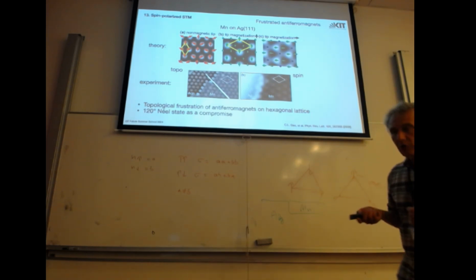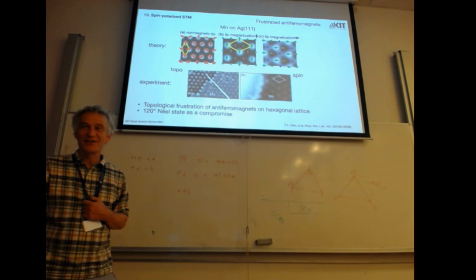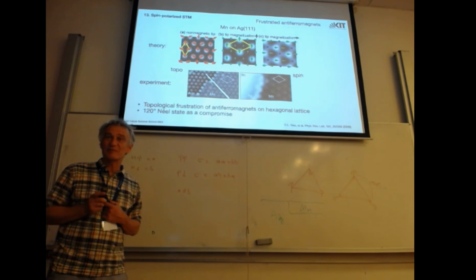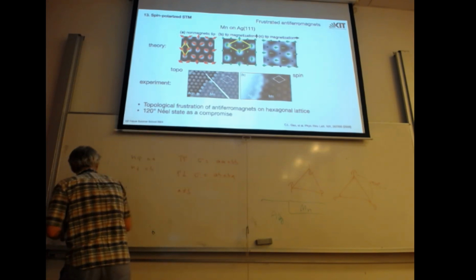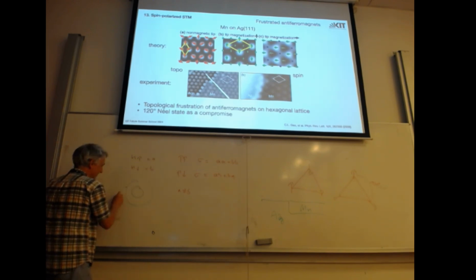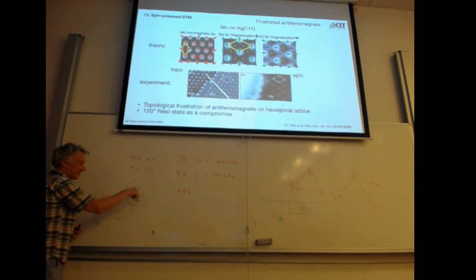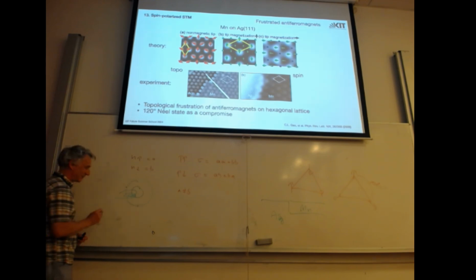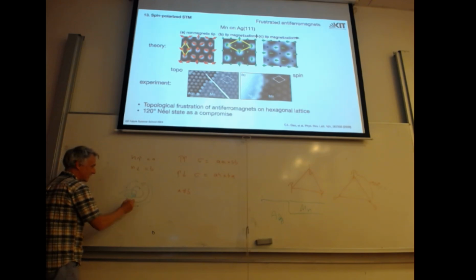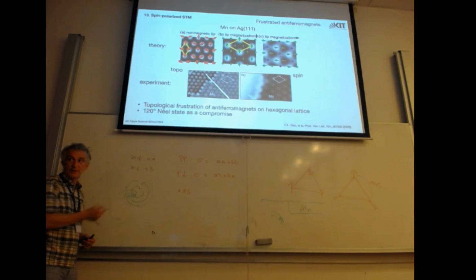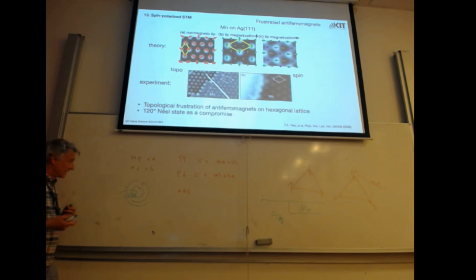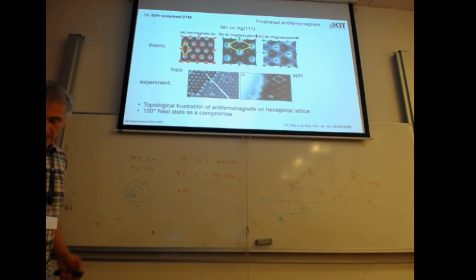Yeah, particular. There are also techniques, actually, I wrote a patent on that, to change the spin polarization of the tip. These are special tips, very soft magnetic. So we make a tip like that. There's a tip, and you have a coil here, and magnetization is either this way or the opposite way. Switching from one to the other, you need only to apply more current here. Then you can actually measure the difference between those two orientations, and then you get a complete separation of density of states. But it's a little bit difficult, this technique. We were the only group on the planet. So, the spectroscopic method I showed you is easier.